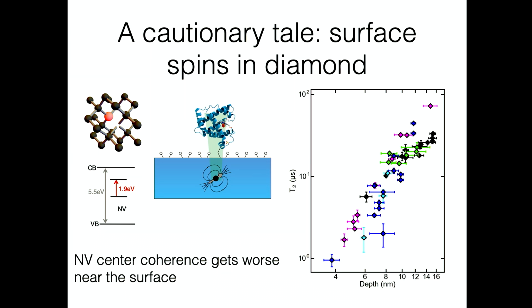And you don't need to know very much about this, particularly for this talk, but the key thing is that it has very long quantum coherence times, even at room temperature. So there are a very large number of groups all around the world, including several at Harvard, that are working on using this as a quantum sensor. And one of the images that we always put in our grant proposals is you have an NV center under a diamond surface, and you put it within nanometer distances of, say, a protein, and then you can use this thing to do nanoscale magnetic resonance imaging. Sounds very cool and sexy, but nobody can do it.